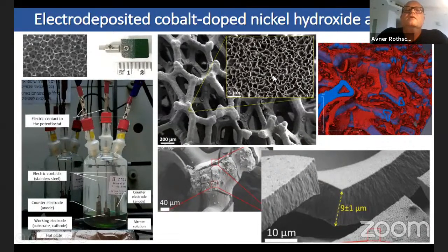And the structure of this layer looks like a coral. So it is basically a nanoflake morphology with very thin flakes. The wall thickness here is about 20 nanometers, which gives you, first of all, the overall thickness is high, is 10 micron, which allow you a lot of active material. So this gives you the capacity. And the short distance for the solid state diffusion that comes from the thin walls give you the high rate performance. And this would enable us to charge these electrodes at high current density, as high as 200 milliamps per centimeter square. That's very high compared to battery electrodes, multiple times, and still keeping high capacity, which obviously both of them are very important for our application.